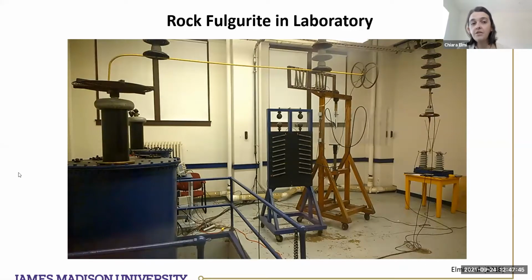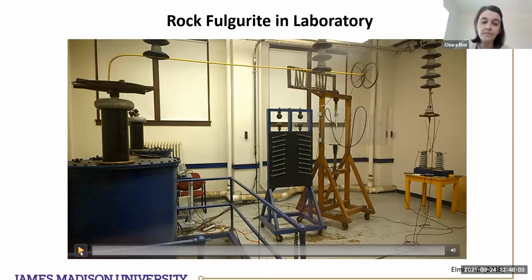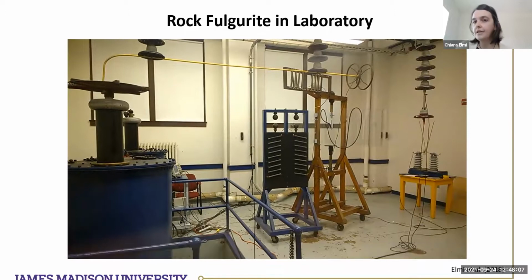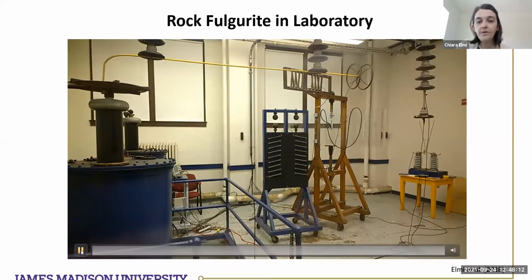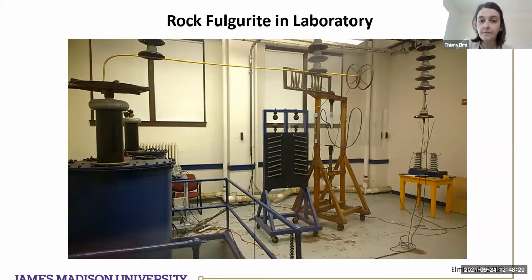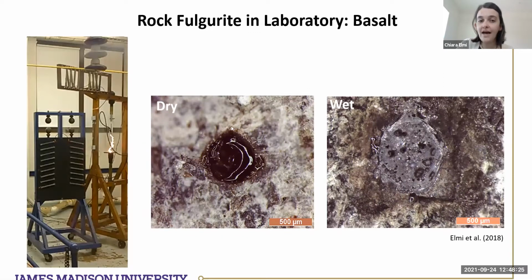But it wasn't enough, because I was looking at the end of the process, but I didn't know about the beginning, the point where the lightning fell down. So what I've done was an experiment in the lab, and recreated the lightning on the rock you see here, so that we were able to study this rock and the fresh fulgurite on top of it in the lab. The result was evidence of a glass crater forming on the surface of this rock. We tried with a dry surface and a wet surface, because you noticed before that the glass had a lot of porosity.